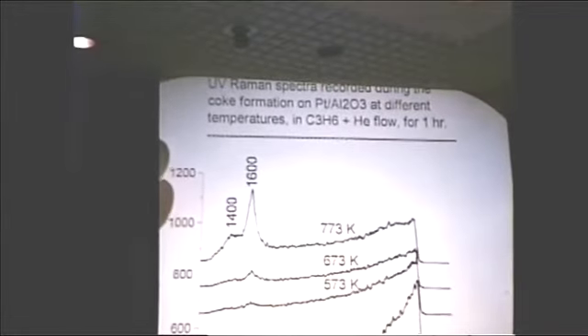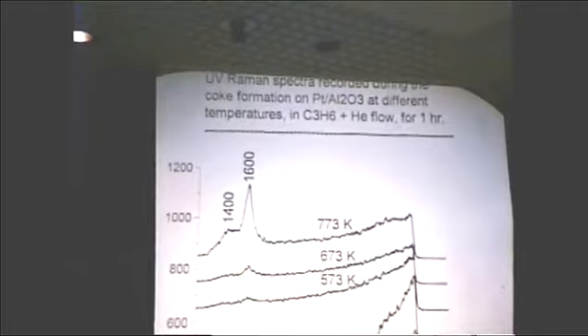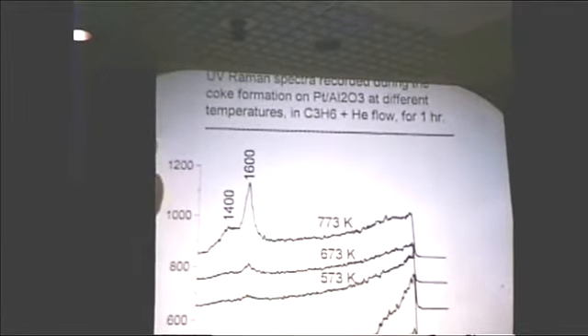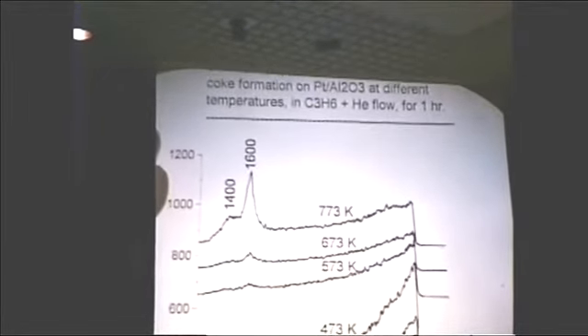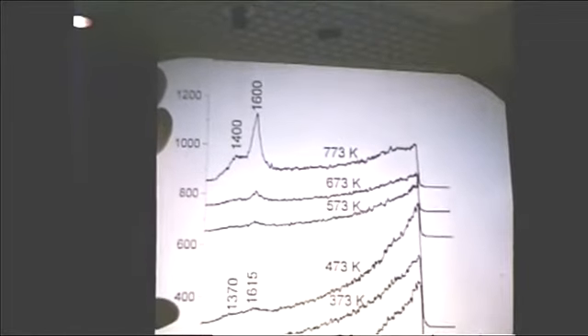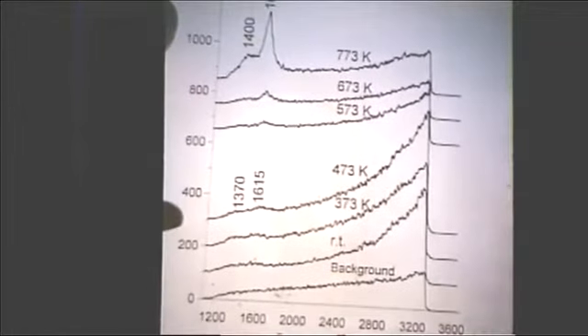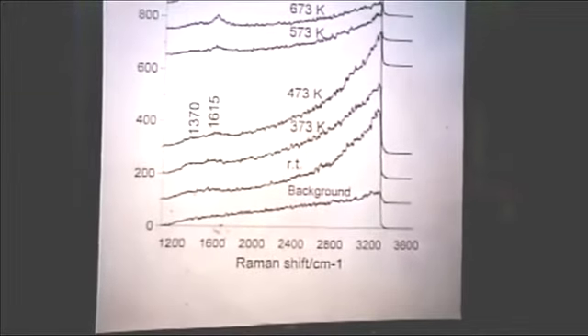Now, we thought it would be interesting to compare these results to a catalyst which does not have the acid sites that either the ZSM5 or the USY have. And so we also looked at a platinum alumina catalyst. Again, this catalyst came to us from Amoco. It was coked originally, but we cleaned it off by burning the coke off in oxygen. Okay, so this is again propylene exposure.